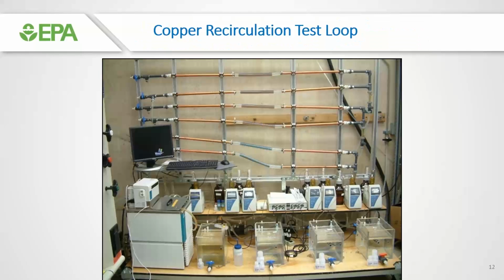Another set of experiments that we did was with copper recirculating loops. Unlike lead, where you have to go out and harvest old lead service lines, because of the complexity of lead service lines, the multiple layers that Simoni talked about and all that play into lead release, these aren't so important with copper. In fact, you can start with new copper plumbing because it's still relevant. People are still putting it in. It represents the worst case scenario. So you could use new pipes to study copper release and copper corrosion and look at strategies to reduce it.